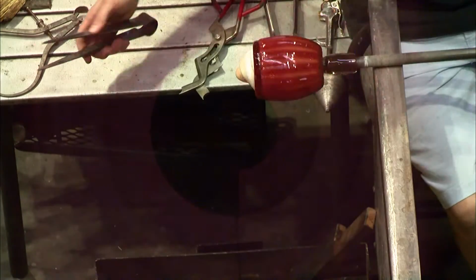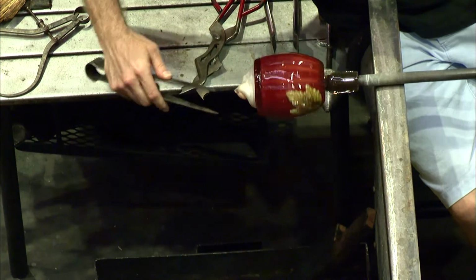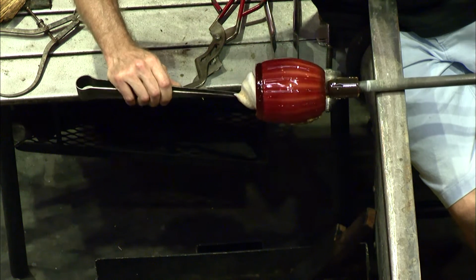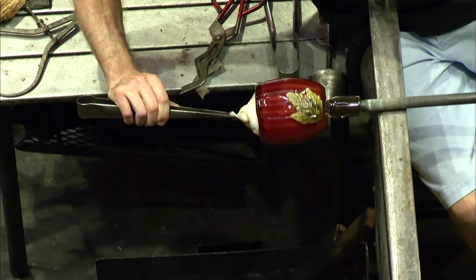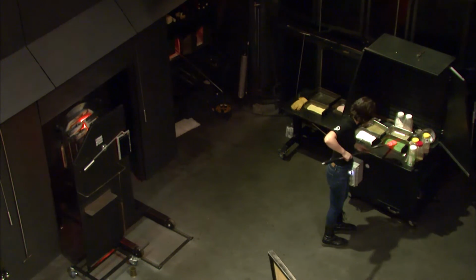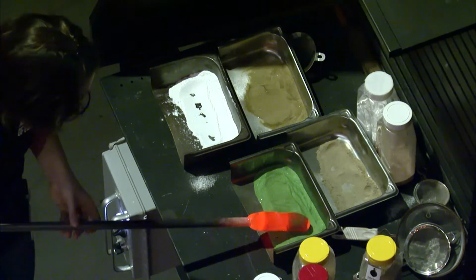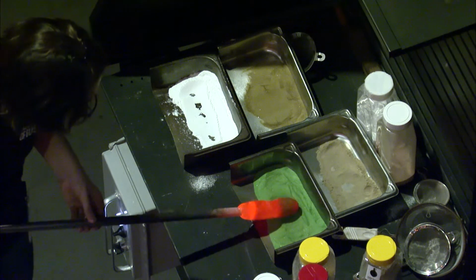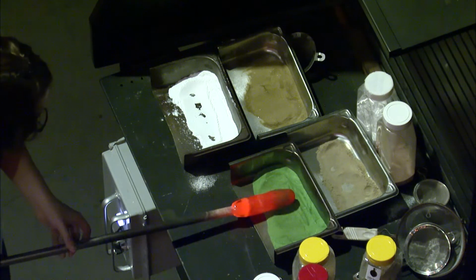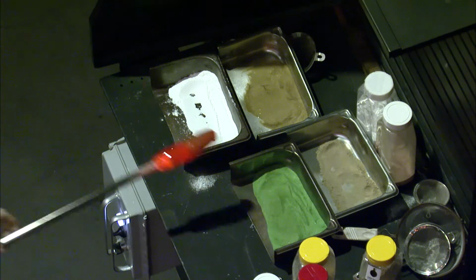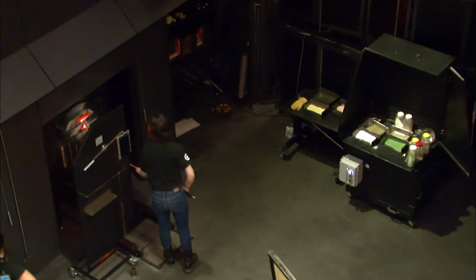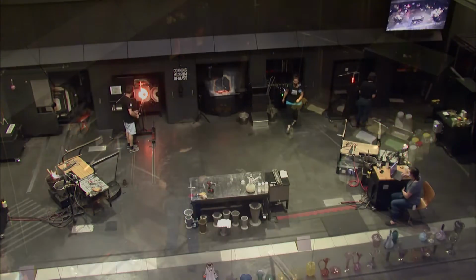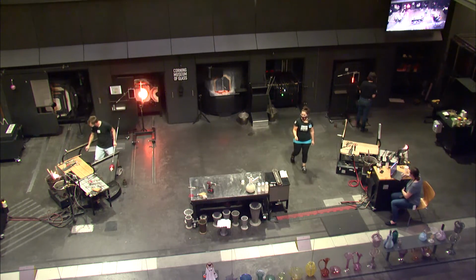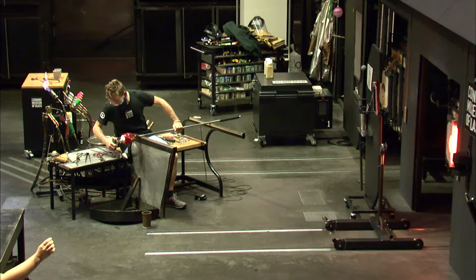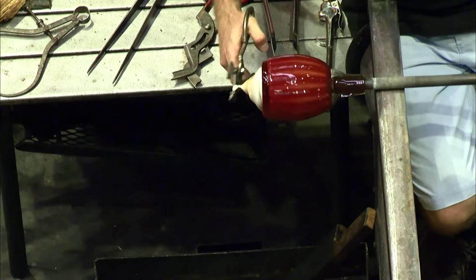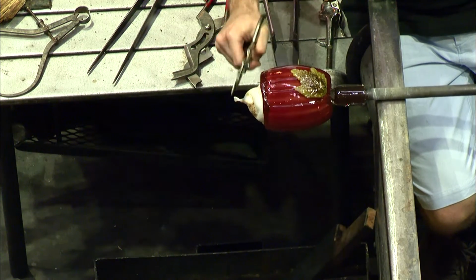And then our question was, why doesn't the glass stick to our optic molds? We've got the glass on the end of metal pipes and punties, and it sticks to that, and it doesn't stick to our optic molds. The reason for that is that the pipes and punties, I don't know if you can see the reddish glow here, are preheated to about half the temperature of the glass. Hot glass sticks to hot things. So it's going to stick to the hot metal of that pipe, but it doesn't stick to our optic molds because they're cold. They're out here at room temperature, no problem.